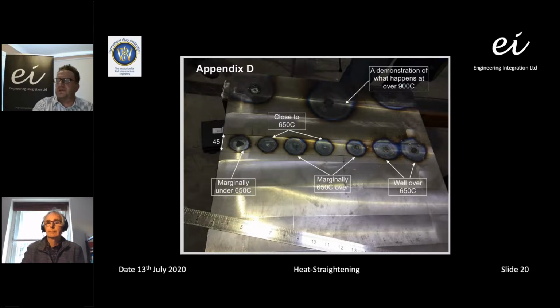We've tried using laser thermometers and what have you, but they tend to be very susceptible to the surface condition of the steelwork and give us very arbitrary readings depending on the surface condition. We have used them in the past, but our preference is to use heating patterns.